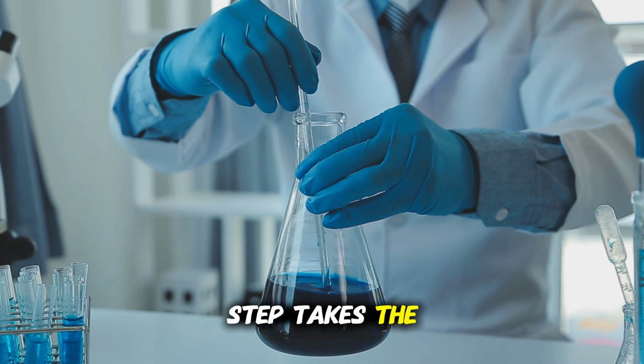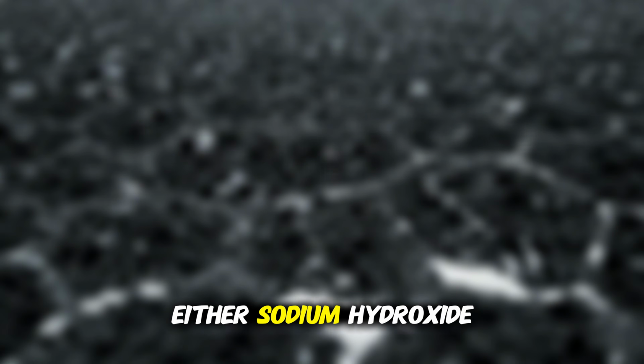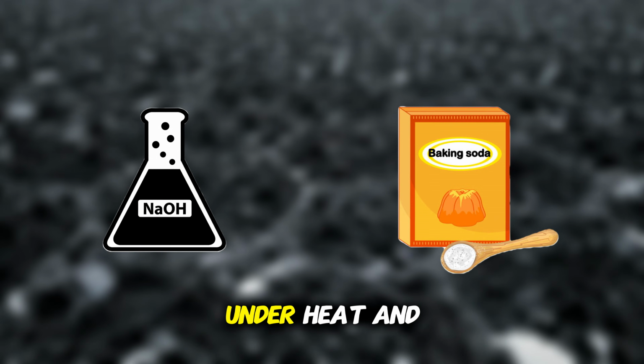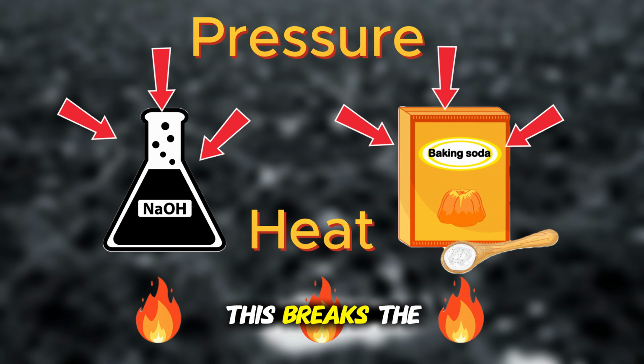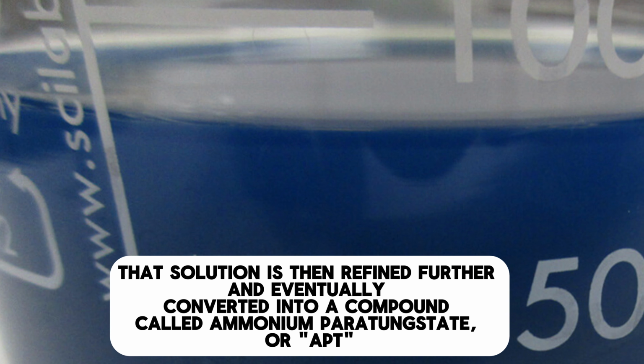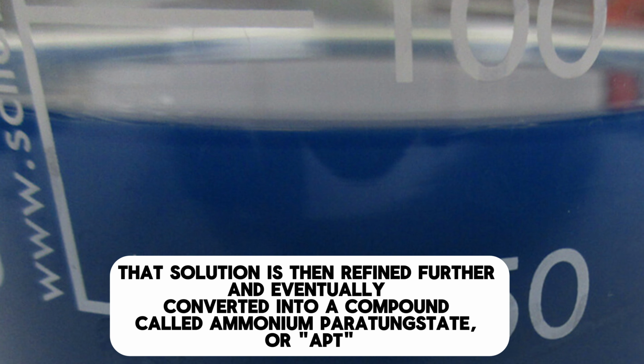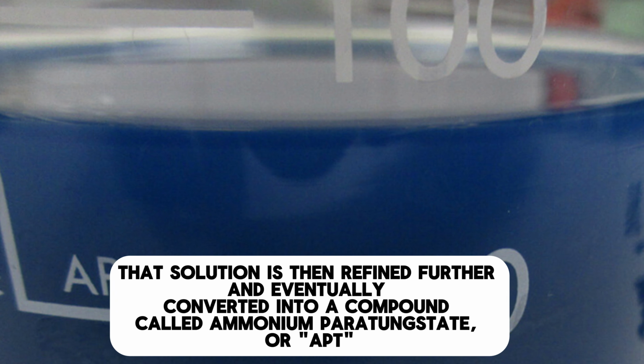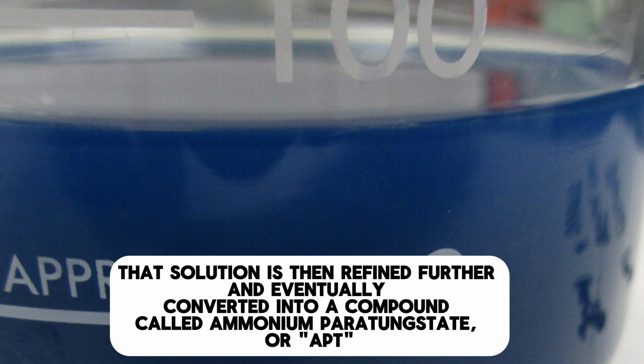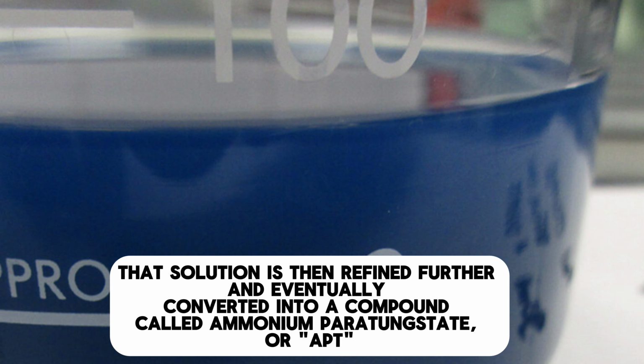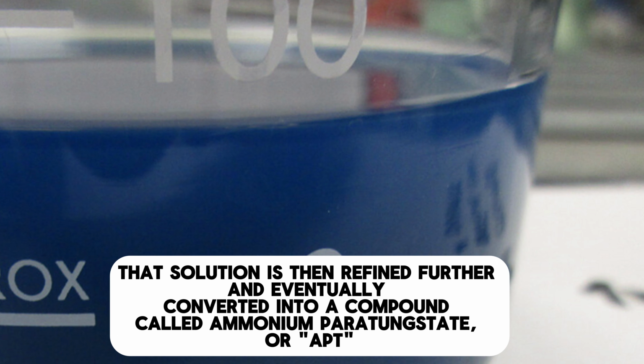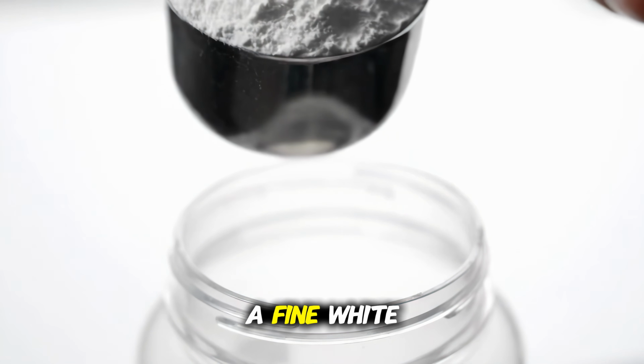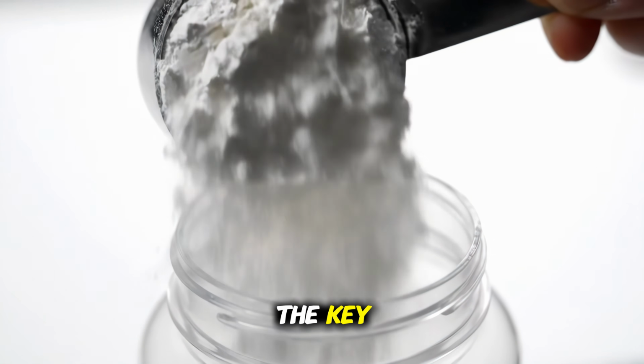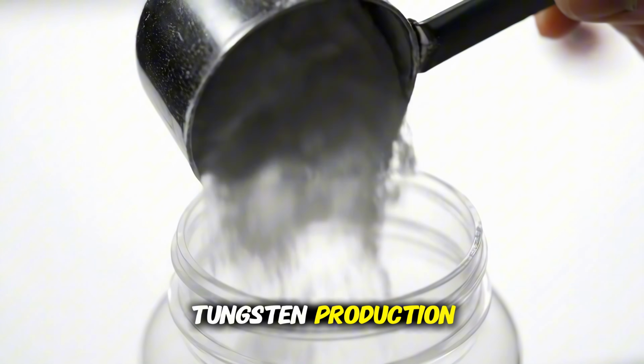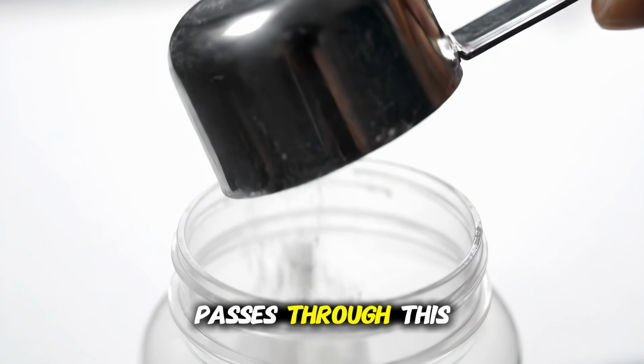So the next step takes the process into chemistry. The concentrated ore gets treated with either sodium hydroxide or sodium carbonate under heat and pressure. This breaks the ore apart at a chemical level and produces a tungsten-containing solution. That solution is then refined further and eventually converted into a compound called ammonium paratungstate, or APT. APT looks like a fine white crystalline powder, and it is the key intermediate step in tungsten production. Almost all tungsten in the world passes through this stage.